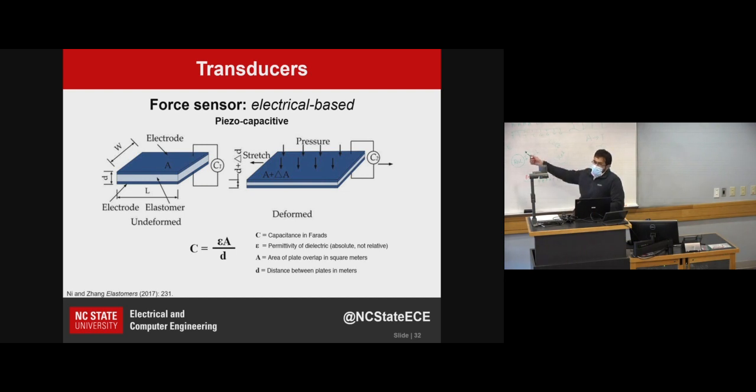So if you want to make your sensor sensitive to forces, be it normal or, let's say, tensile forces where you just pull it, you can't have your conductive trace be too thick, because then it may not be sensitive. It has to be thin. But when you make it thin, you also make it delicate to normal forces as well. So some of that cracking may occur just because of that normal force that is acting. Does that make sense?